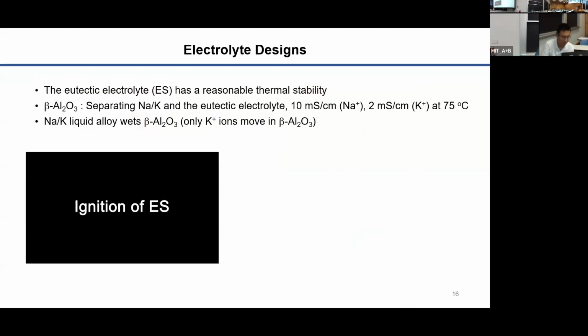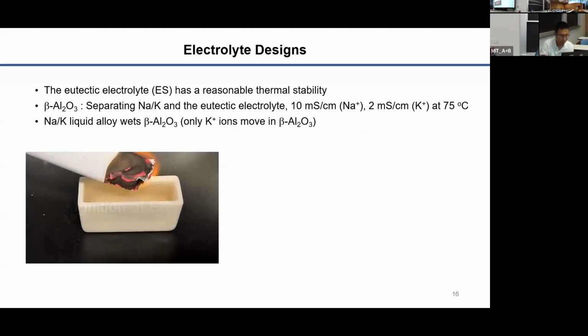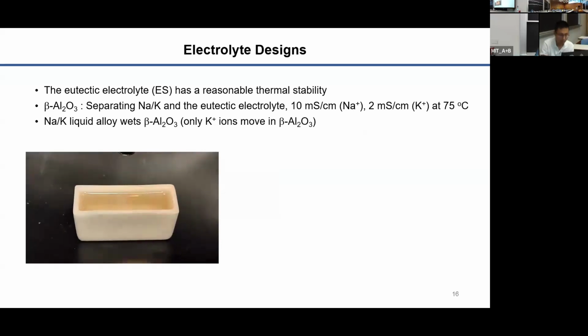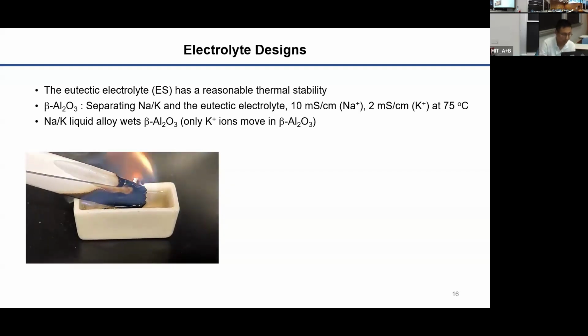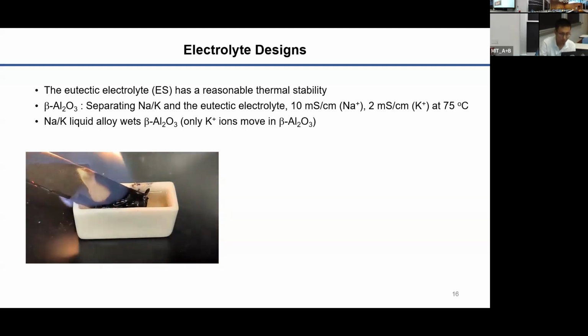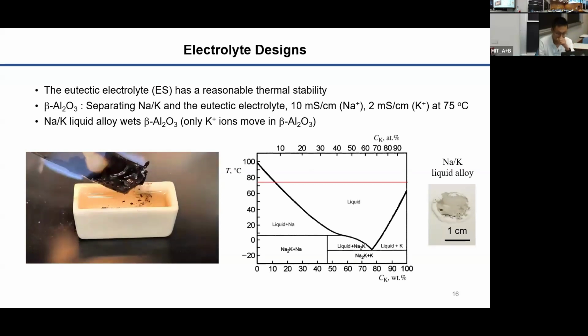This electrolyte also has reasonable thermal stability. I'll just show you, unlike the ether electrolyte, which is very flammable and burns fast. And we have a working temperature of 75 degrees Celsius because at room temperature there is a wetting problem. At this temperature, the beta alumina still has pretty good conductivity for both sodium ions and potassium ions. We also use a sodium potassium liquid alloy instead of sodium metal because it has a very low melting point, so at 75 degrees Celsius it's liquid. And in this case, only potassium ions will move through the beta alumina because beta alumina prefers that. And we solved the wetting problem between the sodium potassium liquid alloy and beta alumina really well.